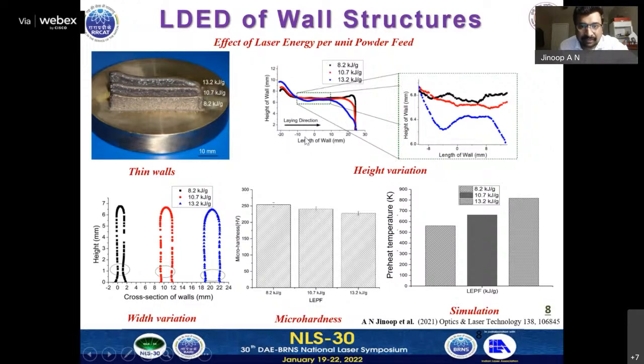So we could see that the variation in the geometry happens along the length and at different LEPF values. And we could see that the stability is more achieved at the lower LEPF values. However, in terms of width, we could see that the width increases with an increase in LEPF, and we could observe a necking phenomenon that happens at the lower layers, mainly because of the reduction in the powder catchment at the lower layers.